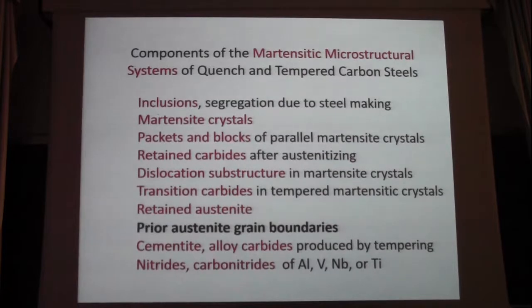Now, here are the components. When we talk about microstructure, here's a list of the many components of a hardened microstructural system. Inclusions, they come with steel making. They are generally negative with respect to fracture. The heart of the microstructure are the martensitic crystals. How do we harden? We heat into the austenitic range at high temperatures. Austenite, a face-centered cubic structure, is stable. But when we cool that, when we quench that, it transforms to a body-centered crystal structure. And that is martensite. And martensite does the hard work.